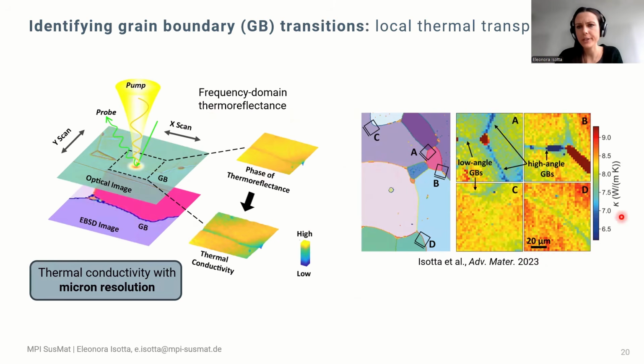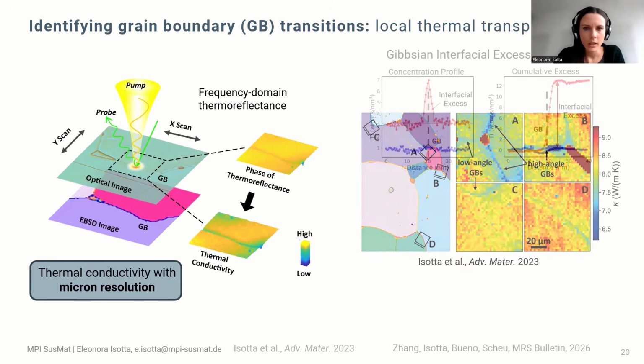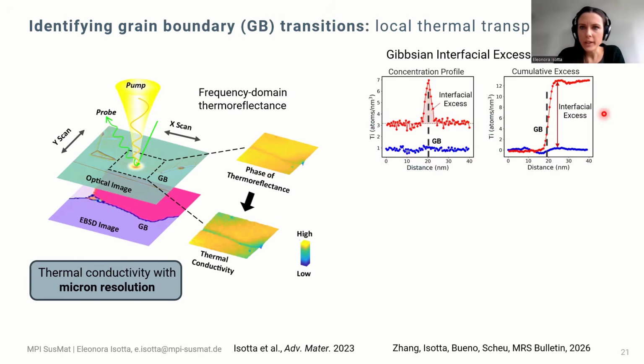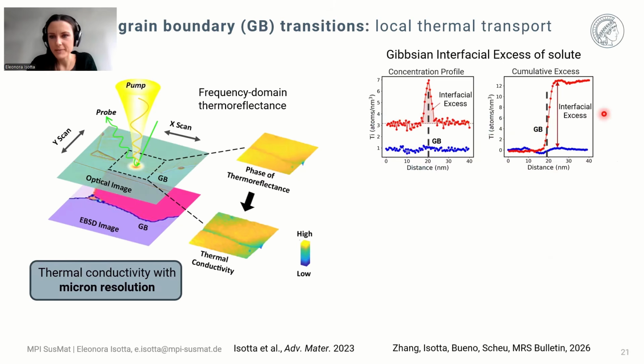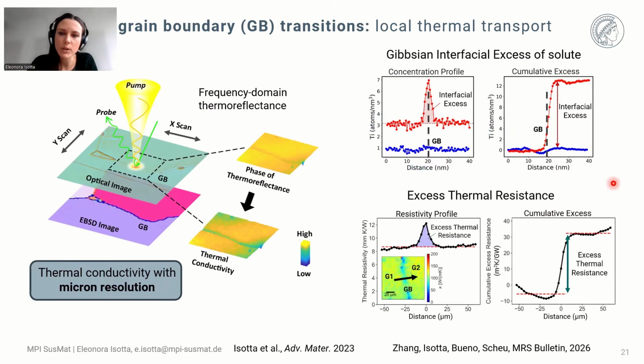As you can see here in the first work that we have published, individual grain boundaries in tin telluride were measured. And when we have these images of thermal conductivity at the grain boundary, what we do is employ a similar method of the Gibbsian interfacial excess of solute that we have seen before to derive what we call the excess thermal resistance.